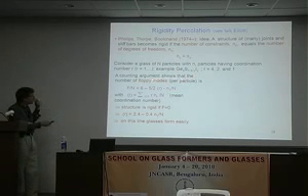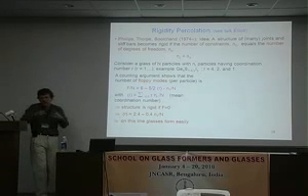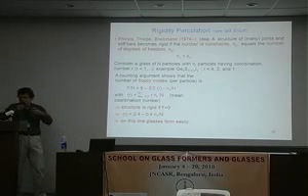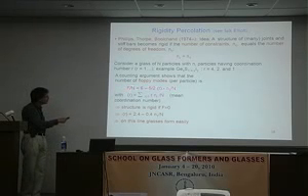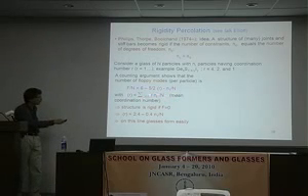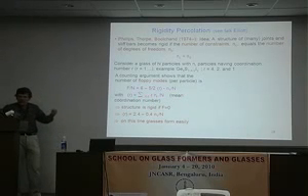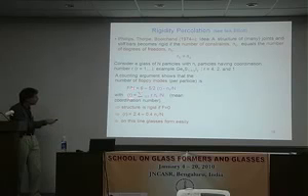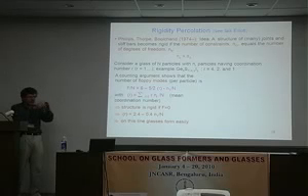Then the number of floppy modes, that is to say, of motions that you can do for free so that you are not violating any constraints, can be shown to be given by this expression here. So this is the number of floppy modes per particle of the system. It's given by 6 minus blah, blah, blah, where r is the mean coordination number. And since you want to have a glass, that is to say something that is rigid, the number of floppy modes has to be 0, okay? Only then it's rigid. So that's the triangle with 3 bonds.